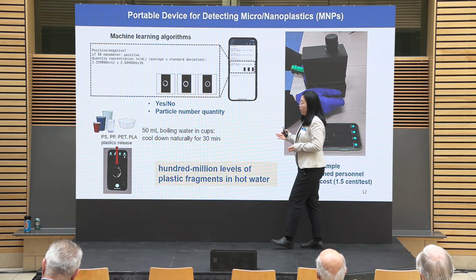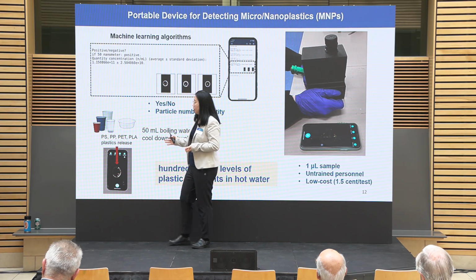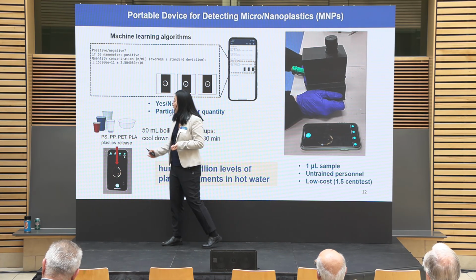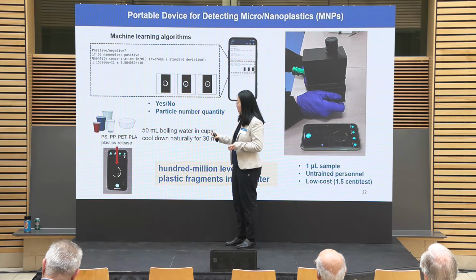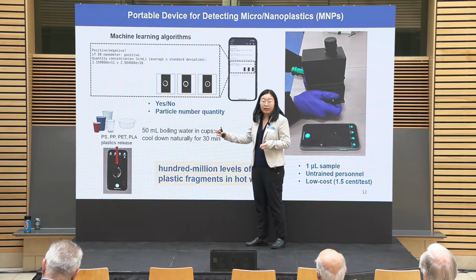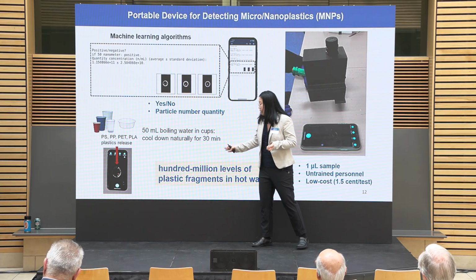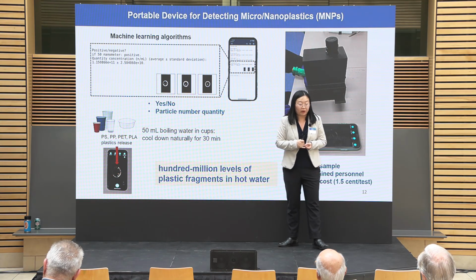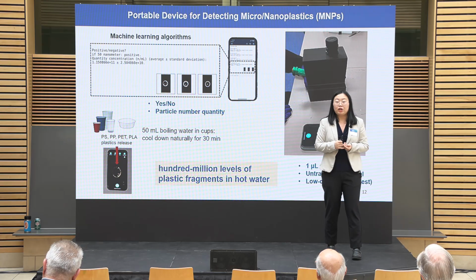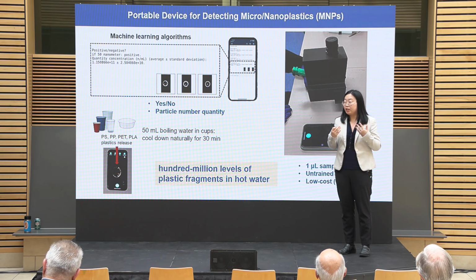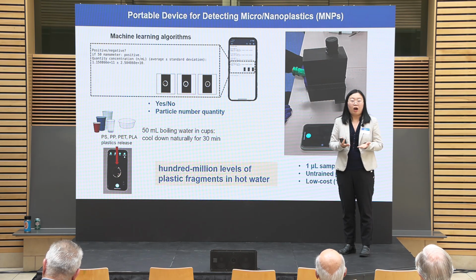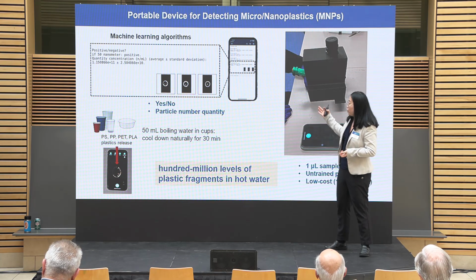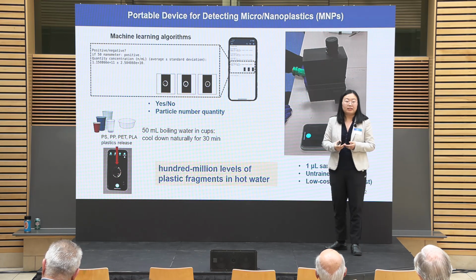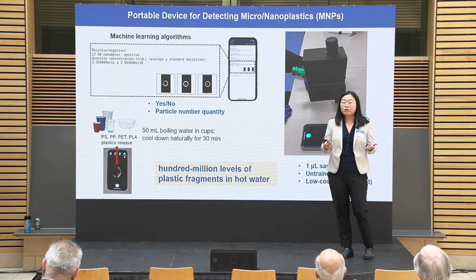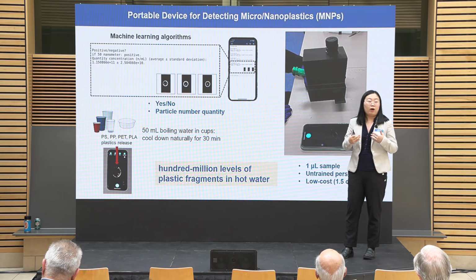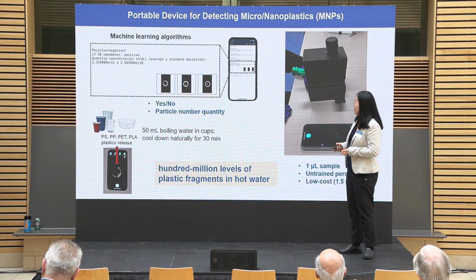Using this method, we evaluated the micro and nanoplastics released from commercial cups, different plastic cups. We add boiling water into the cups and let it cool down naturally. After 30 minutes, we measured 100 million levels of micro and nanoplastics in our hot water. Can you imagine how much micro and nanoplastics you can potentially be exposed to if you just drink hot water or hot coffee? This is a huge issue right now, and researchers are developing different technologies to reduce these risks. Like our lab, we are also working on how to remove the micro and nanoplastics in our human bodies.